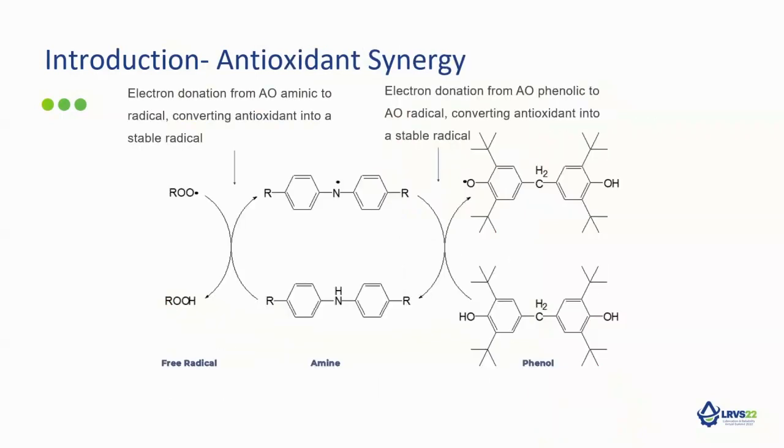So why do we want to qualify the individual antioxidants? This is because they work in something called synergism and will let us understand in great detail how the lubricant is degrading. In this example here, we're showing a free radical interacting with a system which is composed of an aminic and phenolic antioxidant package.